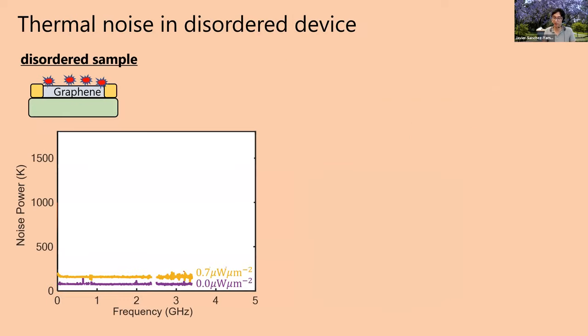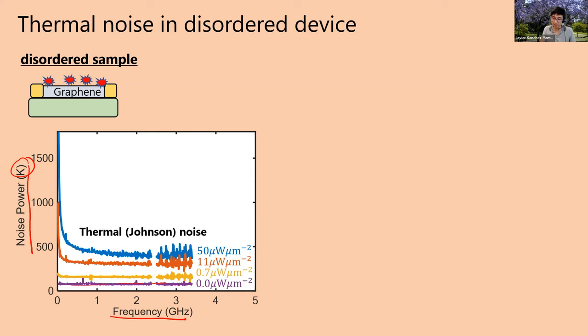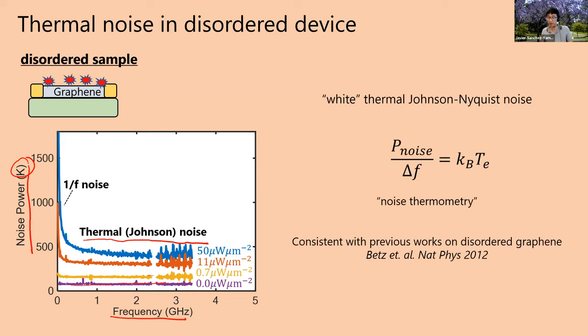First we looked at the disordered device, and if you get some noise signal, you always want to look at the spectrum because it tells you a lot about the origin of the noise. This is the spectrum of the noise, plotted in units of Kelvin, which I'll explain in a second, and the x-axis is frequency. What you see here is that the noise spectrum is very flat at high frequencies, and that's expected because it's thermal noise. Thermal noise, otherwise known as Johnson noise, is famously white. It has a flat frequency distribution, where the power spectral density should be exactly given by kBT. This is a really cool thing where electronic noise allows you to measure the temperature of electrons. The Johnson noise is just proportional to kBT, and this was consistent with what people had previously seen in disordered graphene.